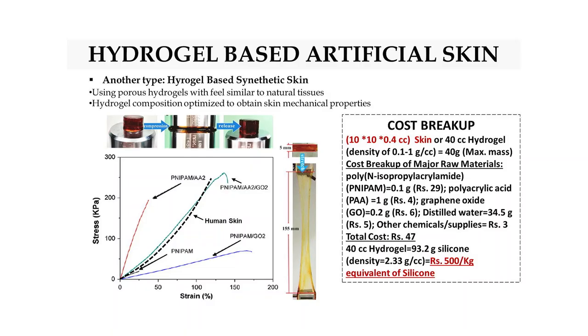Here is an example on the left where you're looking at the stress strain profile. You're looking at the human skin properties, which is in the dashed black color. Then you have one set of chemicals which were mixed to create a hydrogel, known as PNIPAM/AA2, right? But that produced properties which were much greater, or stiffer, than the actual human skin. Then when we changed this to PNIPAM/GO2, graphene oxide, that again created a property which was much lower than the human skin. However, when we mixed PNIPAM, AA2, GO2 all together in the right mixed ratios, which is the right chemistry, then we got a property very similar to the human skin, right?